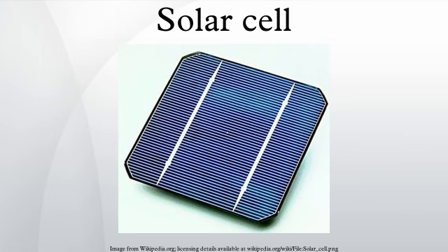The first improvement was the realization that the standard semiconductor manufacturing process was not ideal. The team eliminated the steps of polishing the wafers and coating them with an anti-reflective layer, relying on the rough sawn wafer surface. The team also replaced the expensive materials and hand wiring used in space applications with a printed circuit board on the back, acrylic plastic on the front, and silicone glue between the two, potting the cells. Solar cells could be made using cast-off material from the electronics market. The company started buying up reject silicon at very low cost.